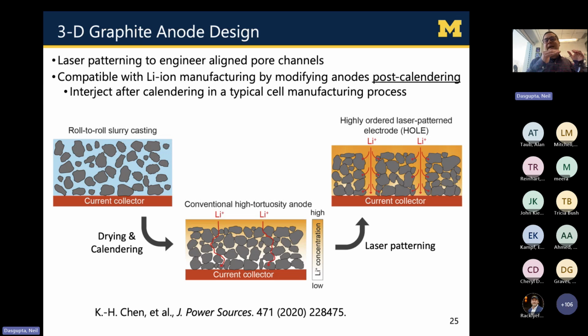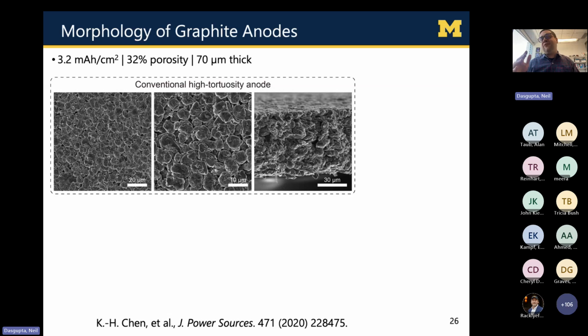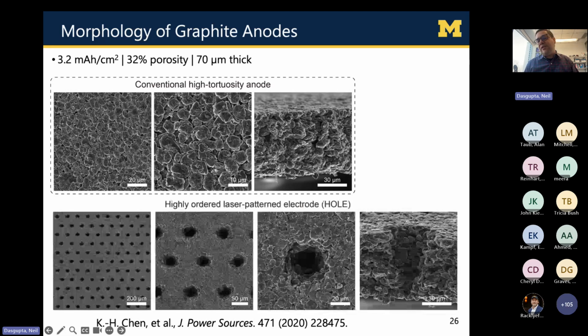This happens after the calendering step. So it's really just one more additional step at the end of the assembly line. And as long as you can do that fast, which I'll come back to a little later in the talk, you can do this without being too disruptive of your manufacturing flow. So again, here are some SEM electron microscope images of these graphite electrodes we manufacture in the battery lab at University of Michigan. I'm showing here electrode loadings of 3.2 milliamp hours per centimeter squared. These are standard porosities and thicknesses for reasonably high energy density lithium-ion batteries.